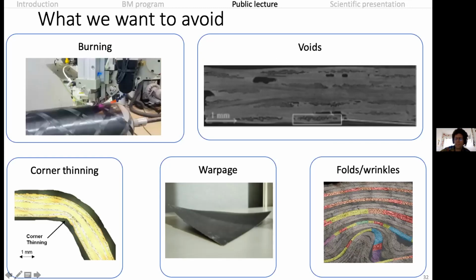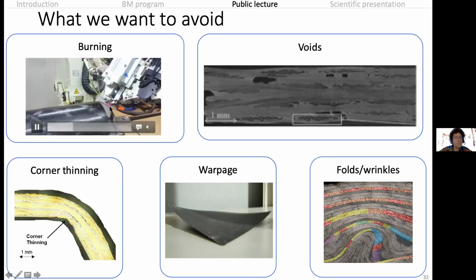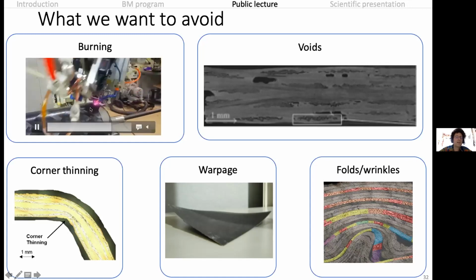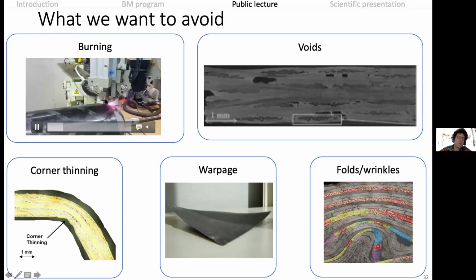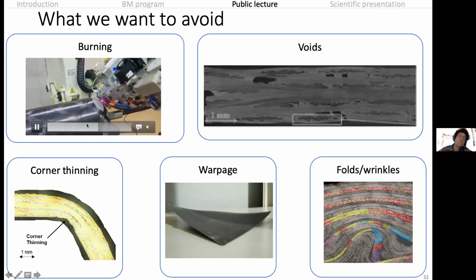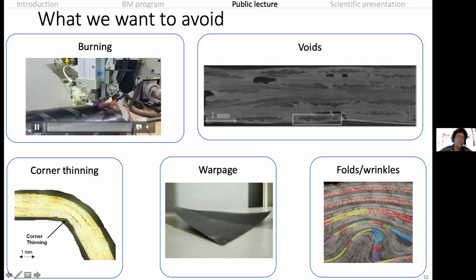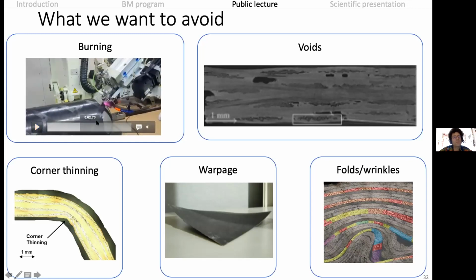And one way to avoid these defects would be, let's say, a basic, time-consuming way: trial and error. In this case, for instance, try to reduce the power because it's burning, and you make a new part, and now the composite is not sticking well, so you have to increase the power, and then you decrease the power, you go slowly. This could be very time-consuming and very expensive in terms of material because you're doing a lot of experiments to find out how we can actually manufacture this part without defects.